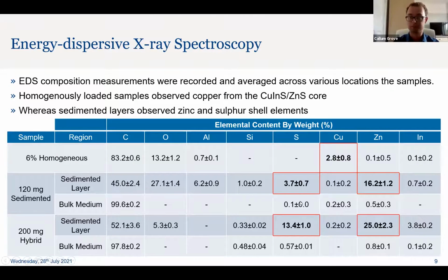The EDS system that we used was accurate to about 0.1, 0.2 percentage by weight. And so any quantum dots in around here in the bulk medium are less than the resolution of the EDS. But highlights from the X-ray spectroscopy: the 6% homogeneously loaded sample showed about 3% copper. Interestingly, we didn't see shell elements for the homogeneous, but we did see core elements for the homogeneously loaded. It's possible that for the sedimented layers the beam didn't penetrate the shell, whereas for the homogeneously loaded layers it did, and we did see part of the core.